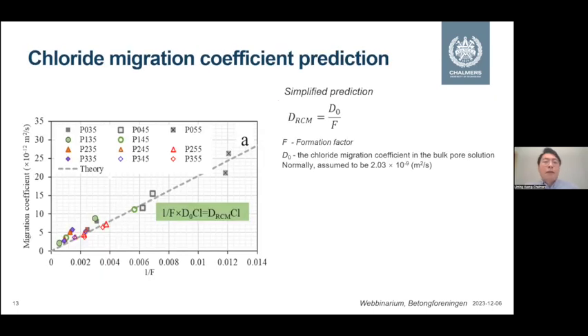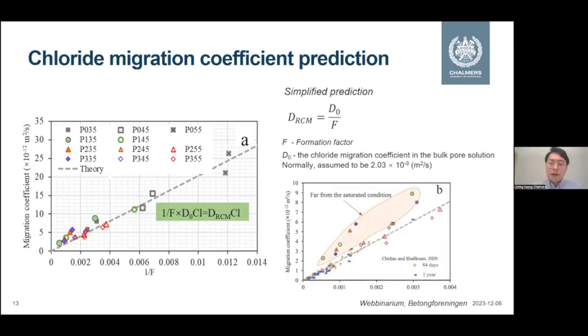It's the same for the chloride migration coefficient. Here we can see a simplified prediction equation based on the formation factor we have monitored. We can predict the effect of SCMs and water-to-binder ratios on the chloride migration coefficient under this RCM, rapid chloride migration, test mode. And not only for our results, but I also put some results from other publications in this predictor curve. It also fits really well on this line.